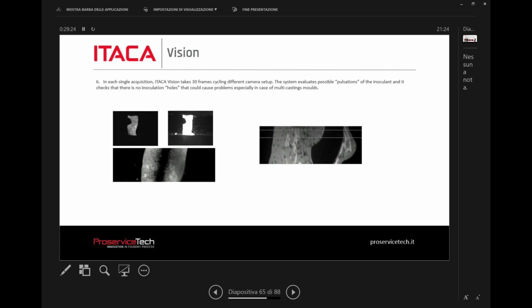And at the moment, our first prototype is working in a German university for measuring the efficiency of the stopper design. Okay. But what happened, for example, here is that the most part of the inoculant is inside here. So when many times this iron splits in two parts, you cannot see with your eyes, but the inoculant goes into the center. So you think that you are inoculating at 0.1%, but at the end you are inoculating 0.05 if you are lucky.